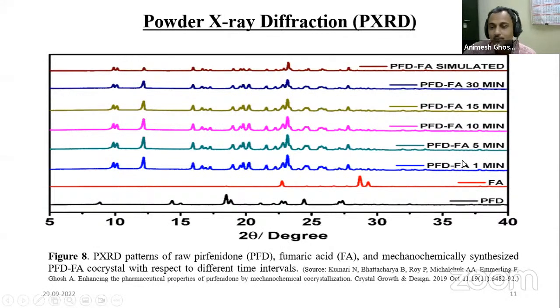So we tried 1 minute, 5 minutes, 10 minutes, 15 minutes, 30 minutes. And if you see, within 1 minute, if we grind it, pirfenidone and fumaric acid will form a co-crystal. And upon milling, it won't change its Bragg diffraction peaks. That means these peaks are retained. And this is quite similar to the simulated pattern, so we can say the crystal lattice of the single crystal and what we have prepared through mechanochemical synthesis are both the same.